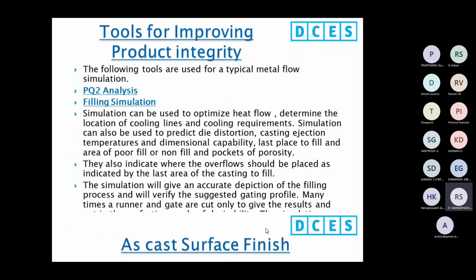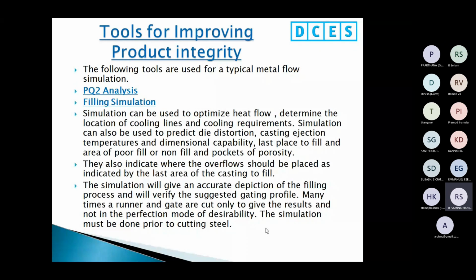The tools for improving product quality. What are all the tools? Two tools can be used. The following tools are used for your typical metal flow simulations. One is PQ square analysis, another is filling simulation. Simulation can be used to optimize the heat flow, determine the location of cooling lines and cooling requirements. Simulation can also be used to predict die distortion, casting ejection temperature, and dimensional capability, last place to fill, and the area of poor fill or non-fill, and pockets of porosity, etc. So simulation can be used to predict this kind of defects in the casting.